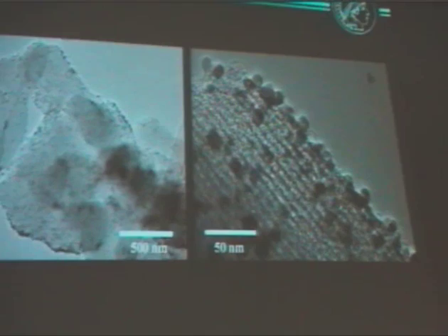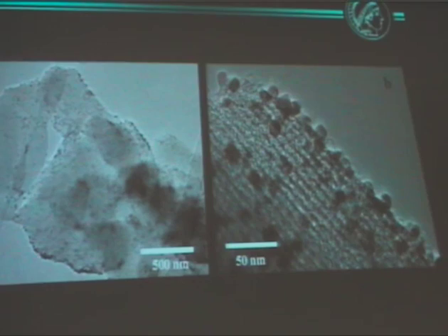If you look carefully, and I'm not sure whether people in the back rows will recognize this, here is actually a very thin structure which has the same size as the dark structures, the cobalt particles, which is hollow. This was an imperfectly protected cobalt particle where the cobalt has been leached out of this hollow carbon sphere, and we just remain with the hollow carbon sphere left. But we lose only about 15% of the cobalt. The rest stays in there, gives the material magnetic properties.